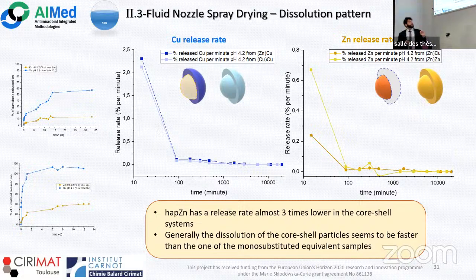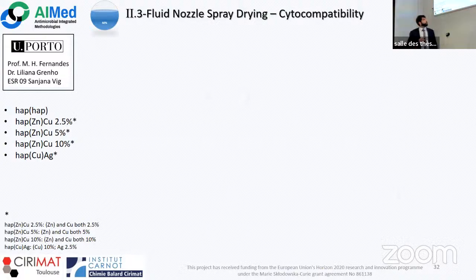But nonetheless, we see that the zinc in the core is so segregated that it has a release rate that's 3 times lower than its equivalent monosubstituted particle. Then we prepared 4 other particles, with 3 different substituting ratios of zinc copper core shell particles, and 1 copper silver core shell particle.